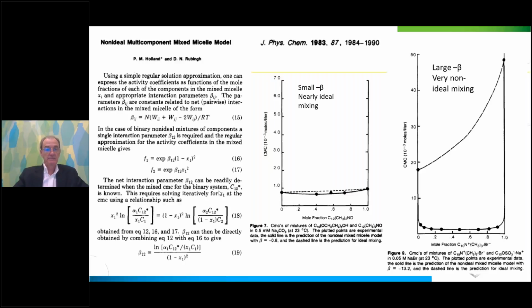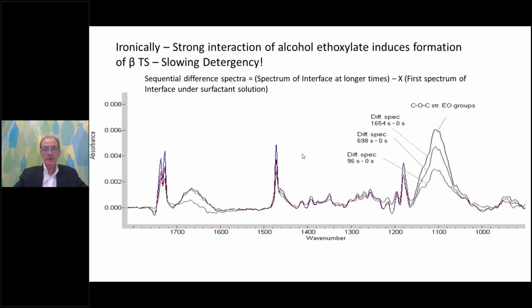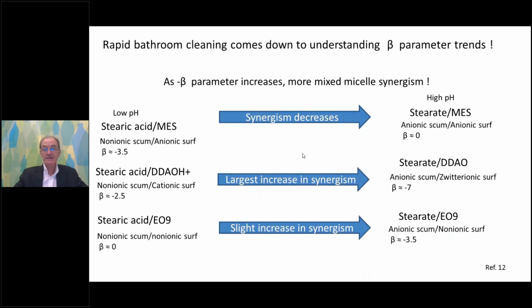The beta parameter, as it becomes more and more non-zero, can be measured directly, very simply, from the mixed CMC of a variety of materials, and then one can calculate what the beta parameter is. It's a measure of non-ideal mixing. What it is not is a rigorous thermodynamic property, and worse yet, it may or may not be constant depending on the composition of mixed micelles, and there are some interesting references on that, as well as Professor Rosen's book.